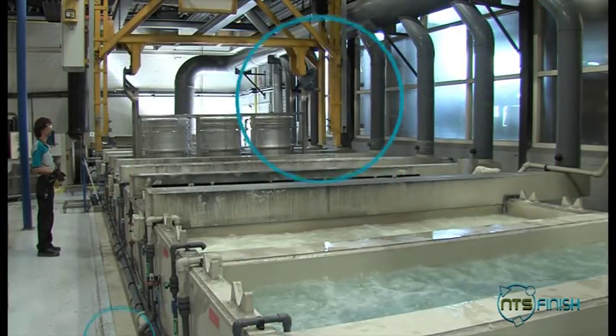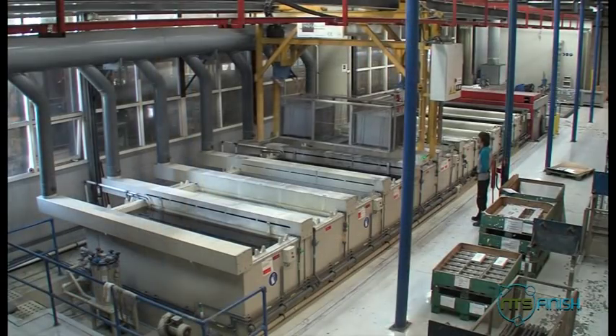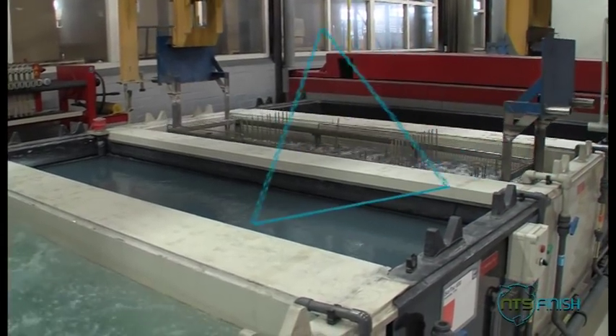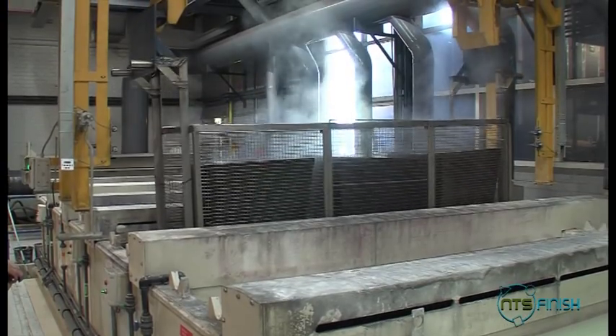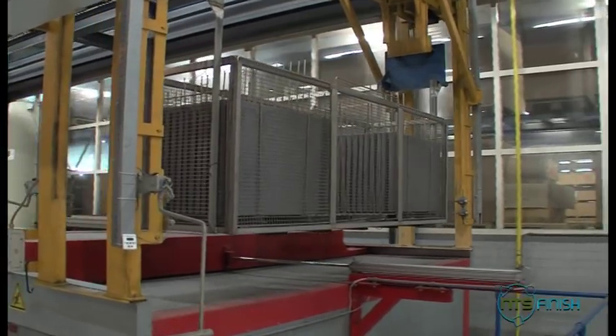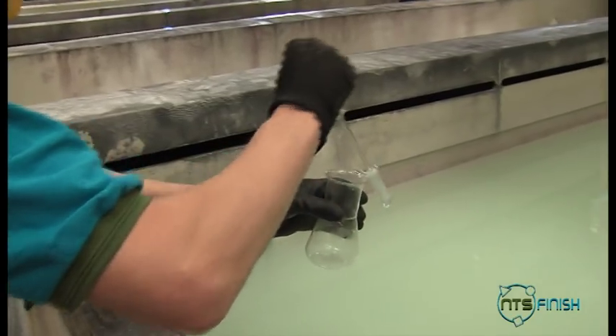It starts here. Pre-processing for chemical treatment allows a thorough cleansing, which finally benefits the adhesion of the coatings. Ferrous and non-ferrous metals up to 3 meters long can be degreased, pickled, zinc phosphated and passivated, aluminium degreased, etched and chrome 3 passivated. This pre-conditioning is a chemical cleansing and prevents corrosion of the metal products.